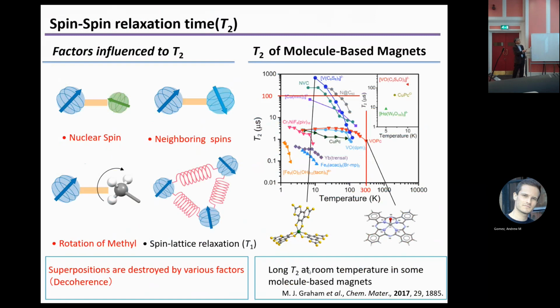On the other hand, in the spin relaxation time T2, the factors that influence T2 are nuclear spin, neighboring spin, and rotation of methyl. So this is a result of molecular-based magnet. T2 more than 100 microseconds is enough for calculation. Some metal compounds, vanadium compounds, show a longer lifetime, more than 100 microseconds. This is very good. And also ferrocyanide, also vanadium, at room temperature. Also, this is very good. So some metal complexes are good candidates for molecular spin qubit.